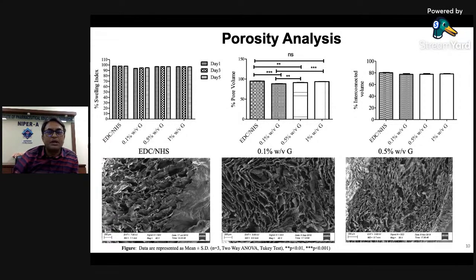When we looked at porosity analysis, there are several methods of doing that: swelling in water, then estimating the pore volume and the interconnected volume, and observing the pore size in the scanning electron microscope. Overall, we did not find much difference between all the concentrations compared to EDC-NHS cross-linked collagen, so all of them were equally swellable.